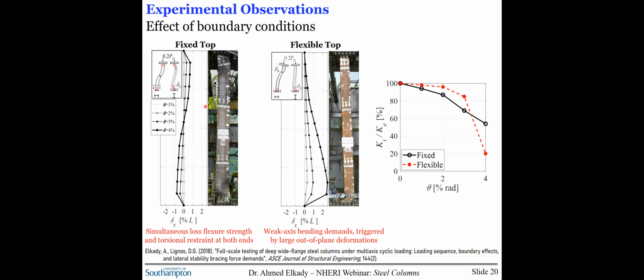If you look over here at the specimen with the fixed top, the column loses the flexural strength and the torsional restraint at both ends simultaneously, leading to almost double the stiffness deterioration level in this plot compared to the column with a flexible top. But with larger drifts, if we look at drifts larger than 3%, the weak axis bending demands that are triggered with these large out-of-plane deformations in the flexible case lead to an accelerated loss in stiffness. Again, as you see here, at one point at large drift, the specimen with the flexible top starts losing stiffness at an accelerated rate.